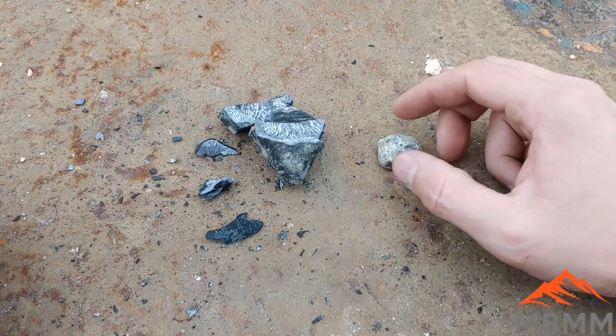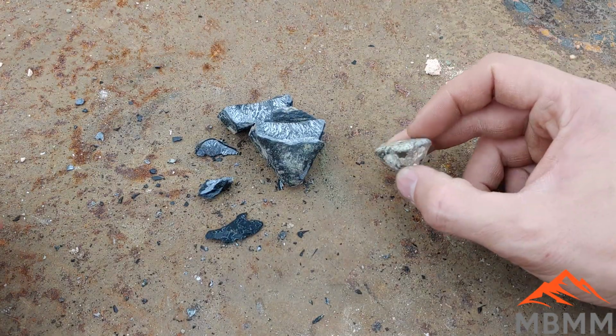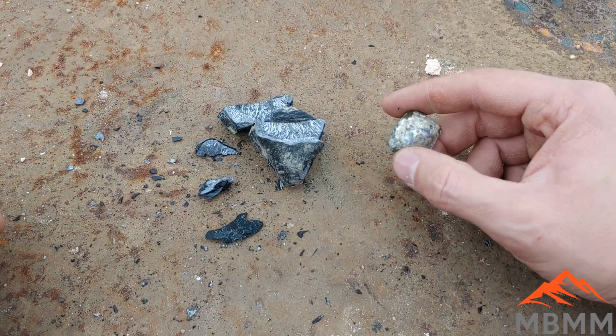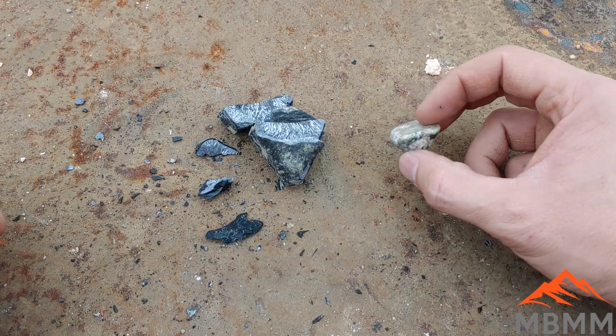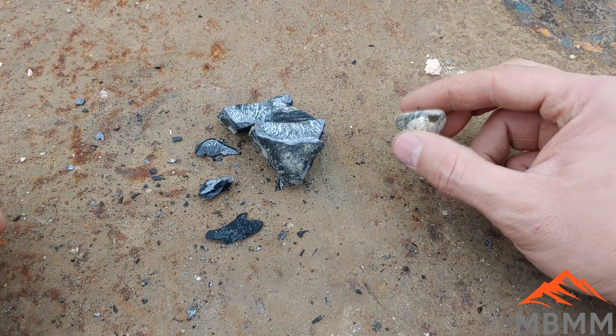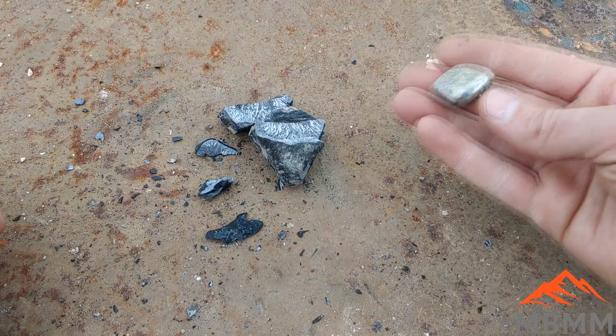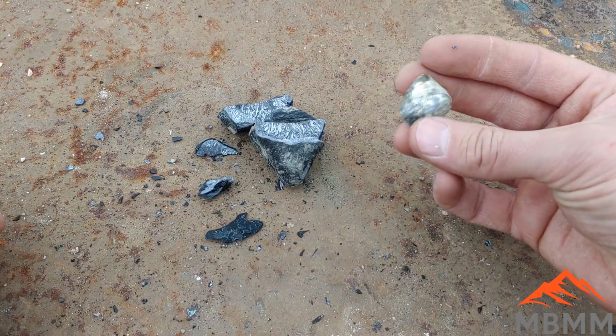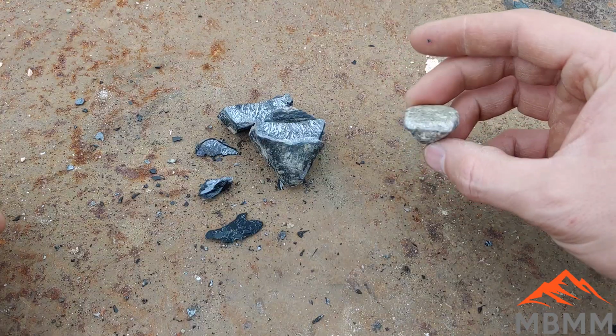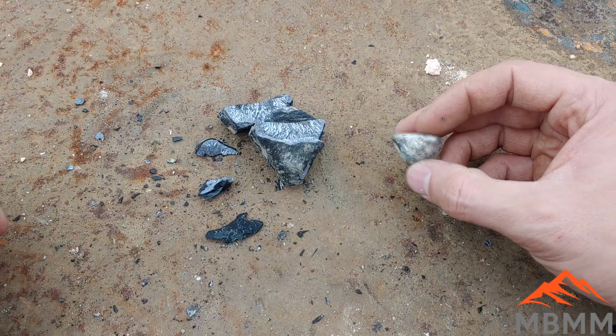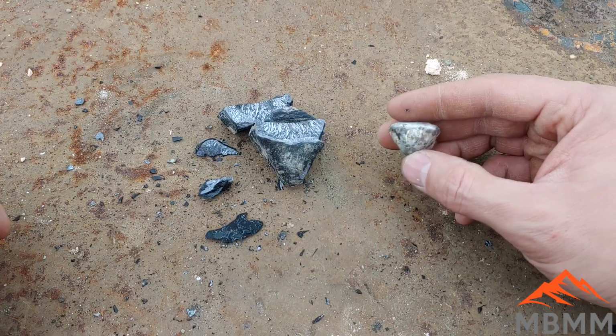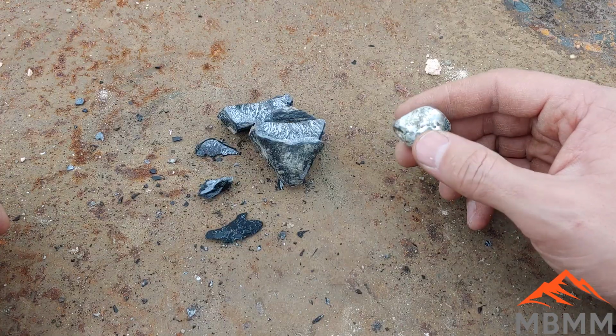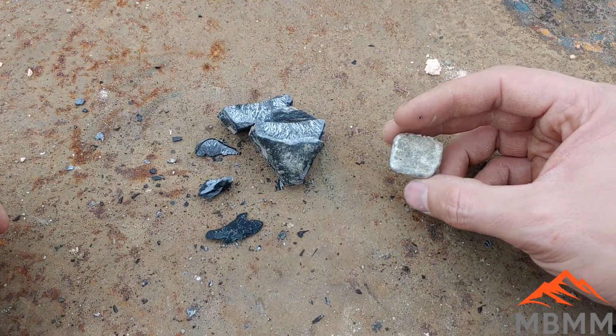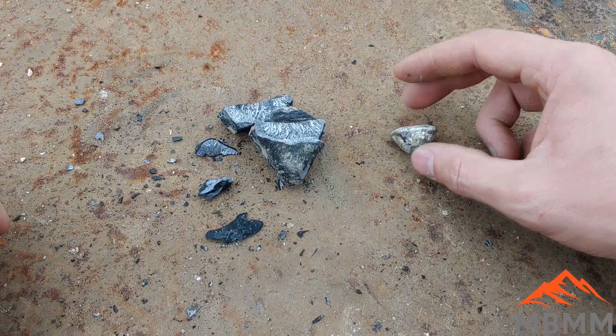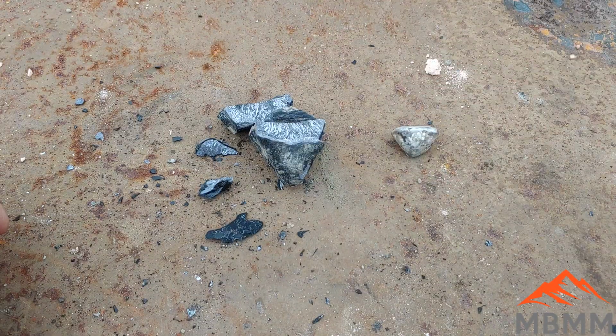All right, guys, so here's two kind of interesting things. Here's a block I got out of the cupel with all those little silver beads. I smelted that down with some borax and soda ash, and I got this little button here in our cone mold. Weighs about 50 grams. I suspect it's about half to a third lead by weight, because I was stirring it with an iron rod, and I could see little lead beads starting to reduce as I stuck my iron rod in.